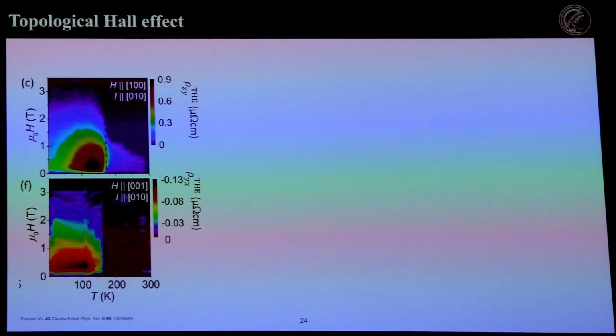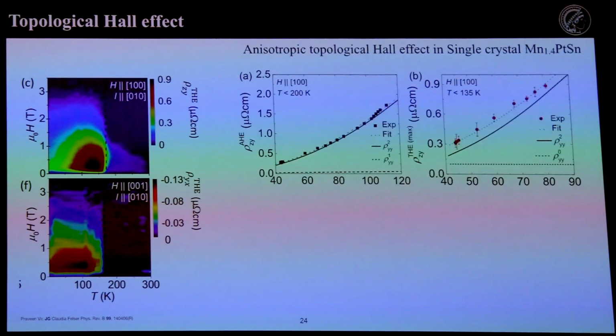To transport, this is actually a real experiment. The student worked very hard to grow single crystals of this material. This is the Mn1.4PtSn. And what he saw was, depending on which direction you apply the field, you get topological Hall effect, as they called it at that time. It's just you make a Hall measurement and you subtract your anomalous Hall and your ordinary Hall, which can be quite tedious, but the student worked very long on it, and he saw 2 different topological Hall transports, and I said, hey, let's do some analysis on this.